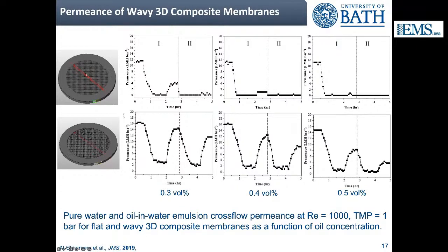And you can see that for the flat membrane, essentially when you go to the second fouling cycle, the membrane is completely fouled and there's pretty much no permeance left. Whereas with the wavy membrane, you do the first fouling cycle. Of course, you have a loss due to fouling, but then when you clean with pure water, you recover most of the initial permeance. Not all, but a significant percentage. You then do the second fouling cycle, and again you recover more or less the same percentage.